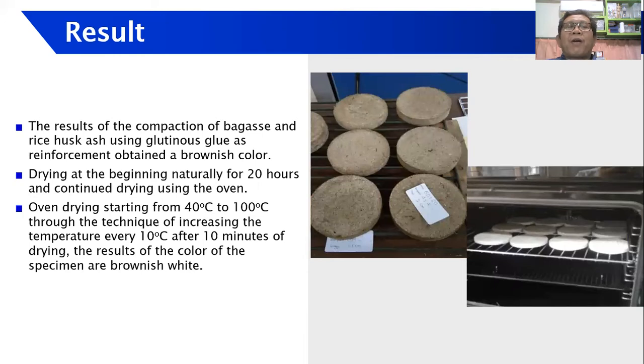The result of the compaction of bagasse and rice husk ash using glutinous glue as reinforcement obtains a brownish color. Drying at the beginning is natural for 20 hours and continues using the oven. Oven drying starts from 40 degrees Celsius to 100 degrees Celsius, increasing the temperature every 10 degrees Celsius after 10 minutes of drying. The color of the specimen is brownish white.